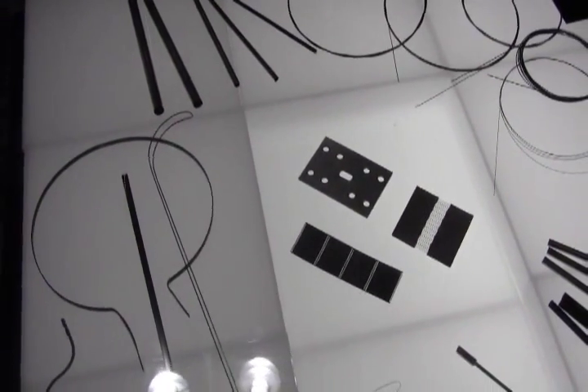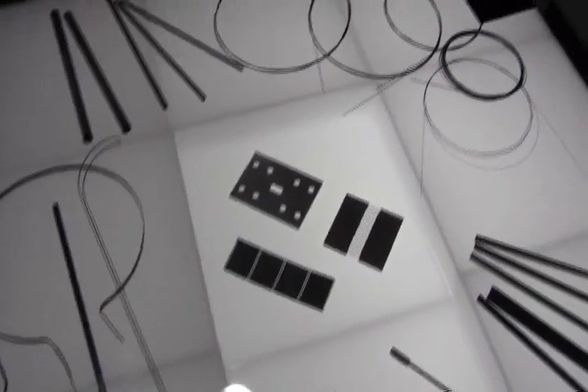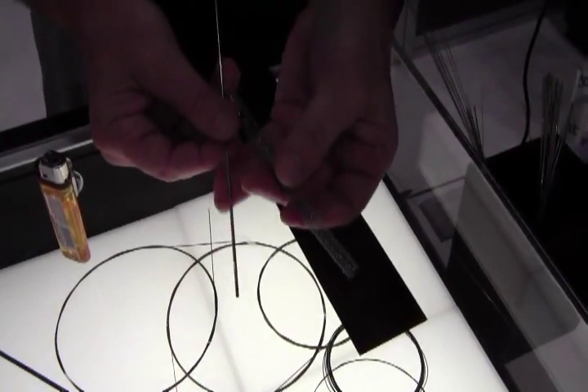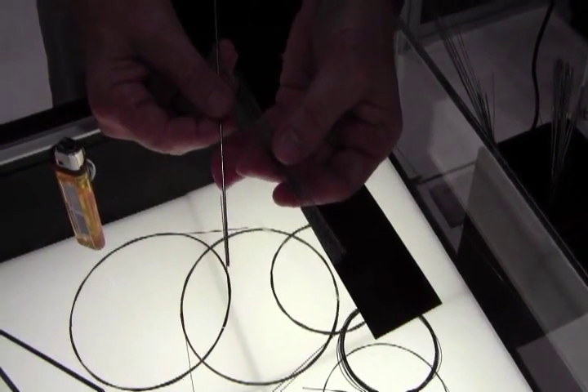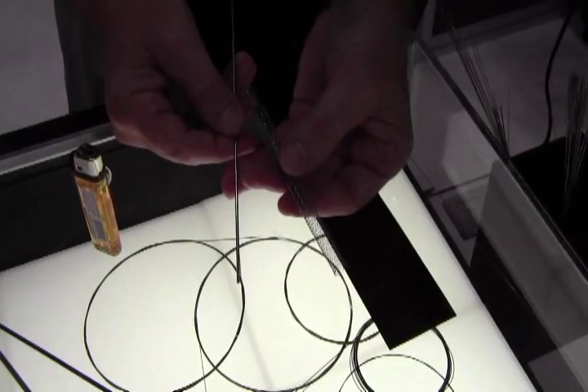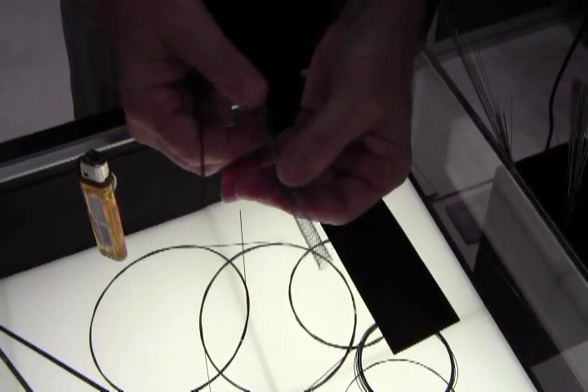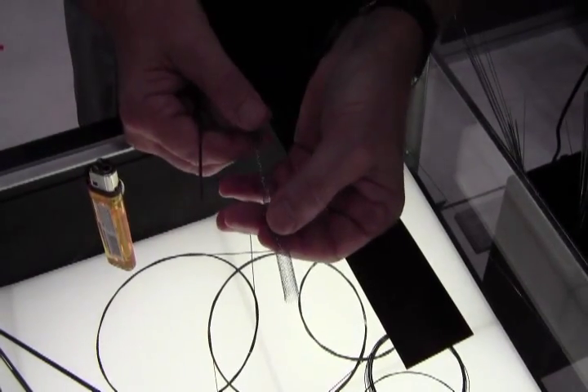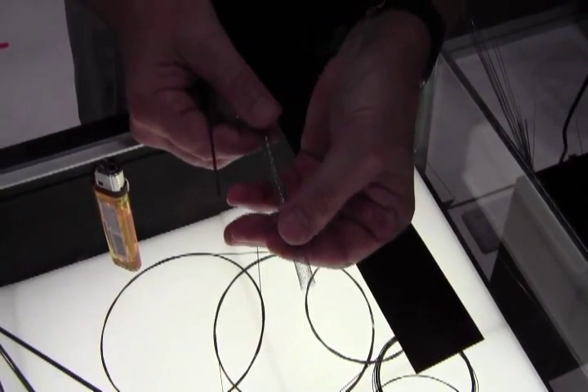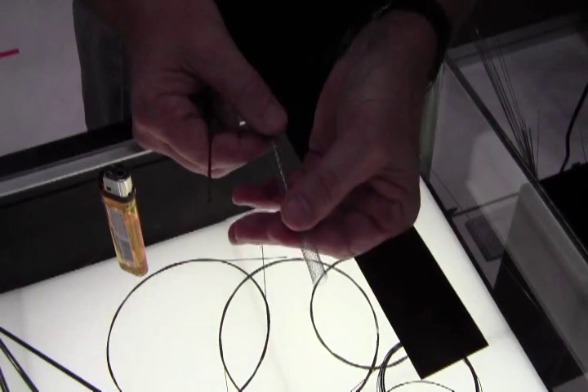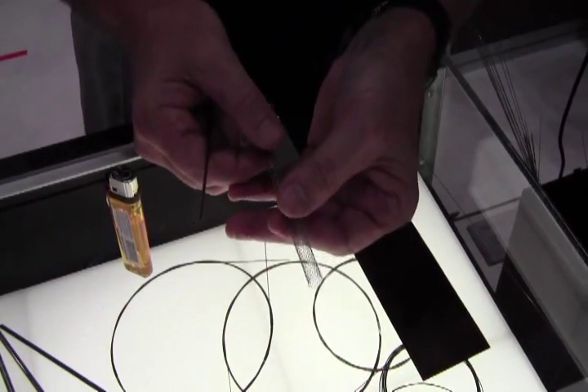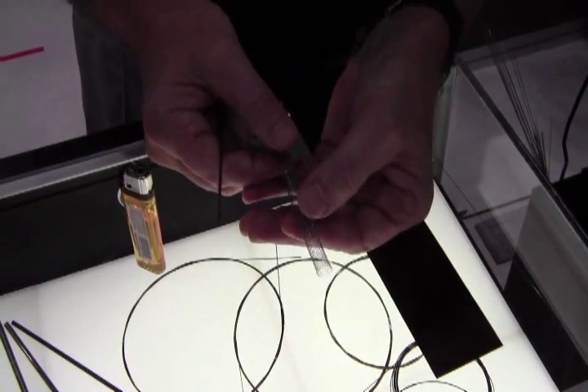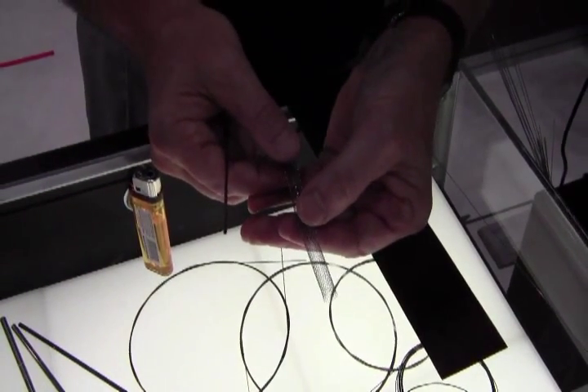One of the major applications for Nitinol in the medical industry is for Nitinol self-expanding stents where you would start with a tube about this size, laser cut, shape set, expand, and then electro polish. At the end of the process you have a nice finished stent that's very elastic, very flexible, and when it's deployed in the body it self-expands to its final shape and holds the vessel open.